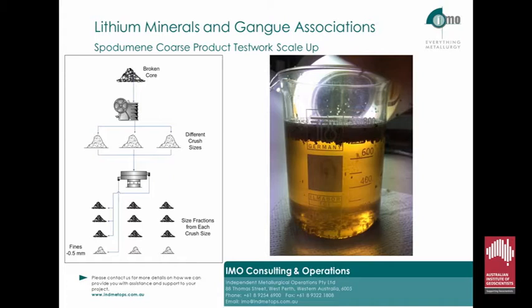The initial test work required for the coarse spodumene characterisation is heavy liquid separation test work in conjunction with mineralogy. Typically a sample is crushed to different crush sizes ranging from approximately 8 millimetres down to 1 millimetre. This crushed material is then sized into a range of size fractions with heavy liquid separation conducted using a range of different specific gravities on each size fraction. Mineralogy is also conducted on size fractions from generally the coarsest crush to narrow the range of crush sizes that require HLS test work.